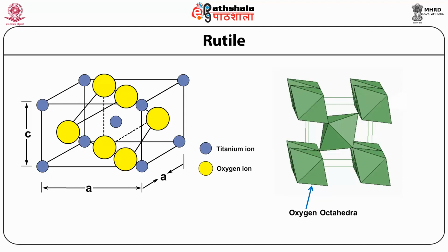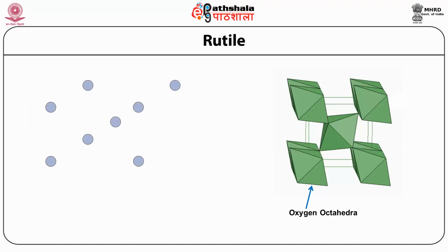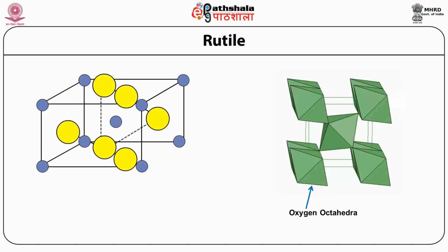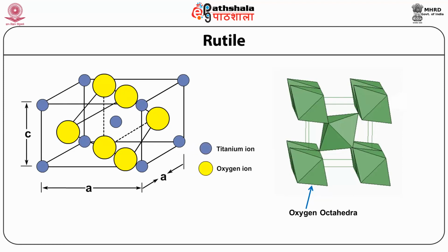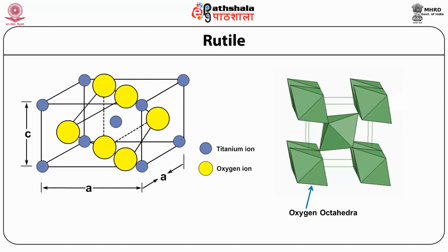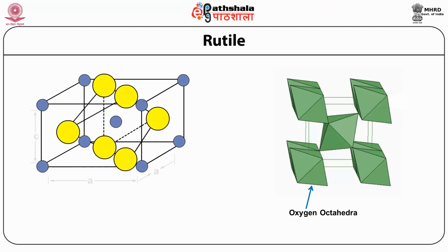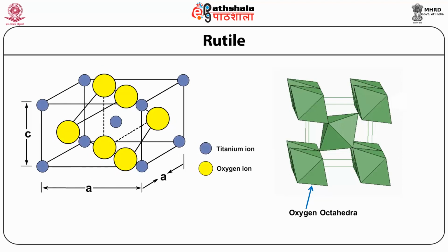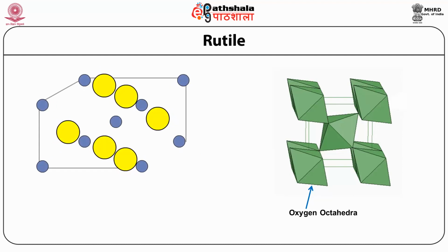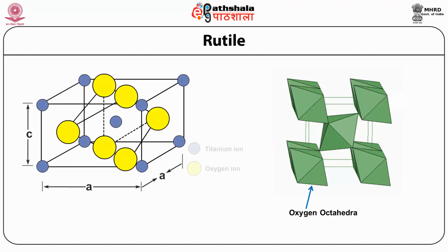Rutile structures most commonly exhibit a columnar growth habit with preferential orientation along their c-axis, where the c-axis is the 001 direction. This growth habit is favored as the 110 facets of rutile exhibit the lowest surface free energy and are therefore thermodynamically most stable. The c-axis oriented growth of rutile appears clearly in nanorods, nanowires, and abnormal grain growth phenomena of